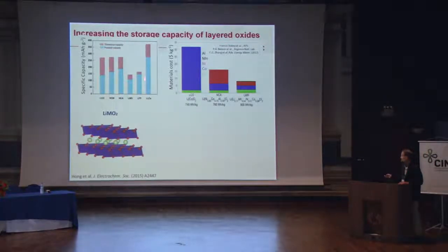So that drives the need to go to what we're calling lithium excess or lithium rich cathodes. These have a higher theoretical capacity, something like 50% higher than the theoretical capacity of conventional cathodes. They're also able to extract significantly more practical capacity. The other thing that's really important in this context is that these materials are actually cheaper. Here are the lithium rich or lithium excess cathodes compared to the conventional lithium cobalt oxide, as well as the nickel cobalt aluminum oxide. You can see here that the cost is dominated by the cobalt. Cobalt's very expensive. There are also humanitarian reasons why you don't want to use cobalt. So that's one of the things that drives the migration from this older material to the nickel cobalt oxides and eventually the lithium rich oxides.